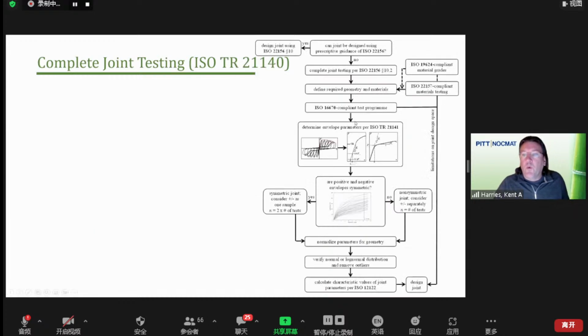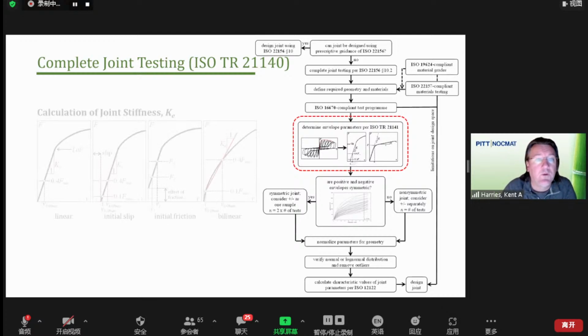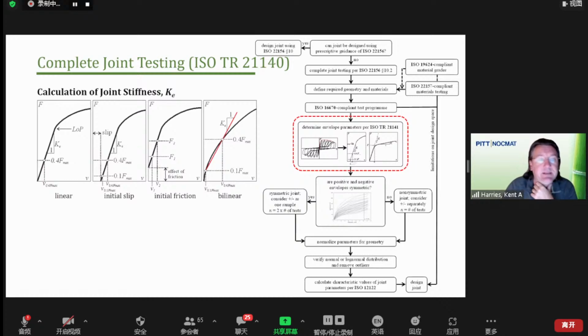So we've done the testing. Now what we need to do is determine the properties of these envelopes. What are the properties of my connection? And so here we look to the technical report 21141, and we have various means of calculating, based on this backbone curve, the joint stiffness. And so if we have an essentially linear portion, we have a joint stiffness. If there's an initial slip, we account for that. If there's initial friction in the joint, so different joints will behave a little bit differently.